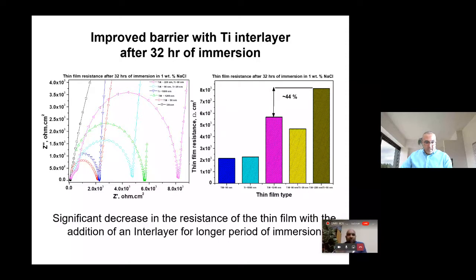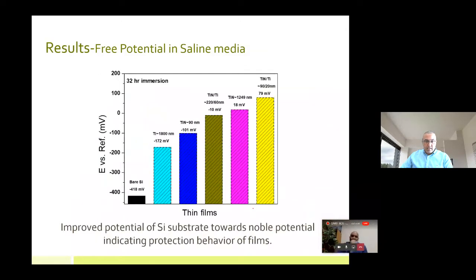So bottom line is that the significant decrease in the resistance that you would see with these nanolaminates when you have an interlayer is basically the period of immersion. So we were able to at least get the sense of how our nanolaminates would behave if we were to put them in a more energy-intensive environment.